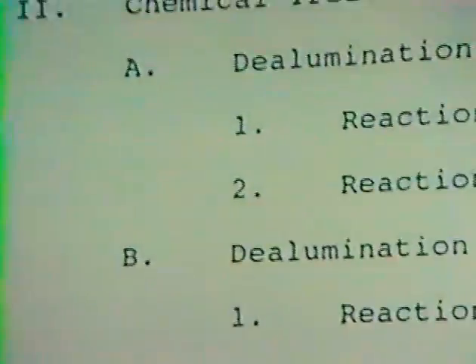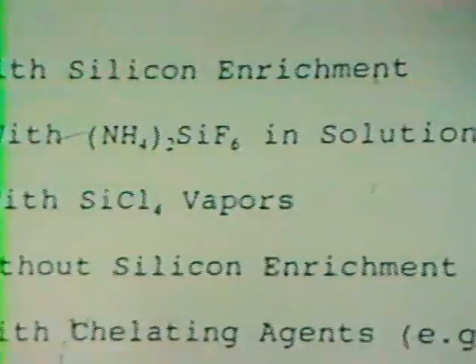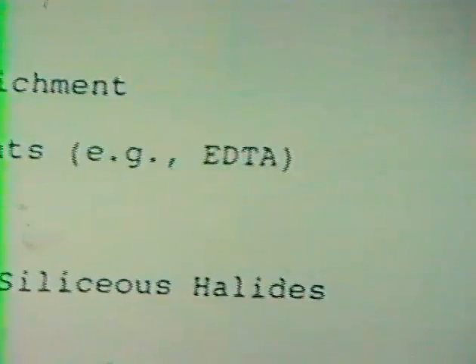I'm now going to pass on for a few minutes to the base of the catalyst, the hydrogenation and the acidic activity. Here I'm going to talk about two major areas: the hydrothermal treatment of the ammonium ion form to stabilize it and remove sodium. This can be sequentially or separately treated chemically to change the silica alumina ratio, by silicon enrichment or by acid treatment to remove alumina out of the structure. There are many changes which occur there.